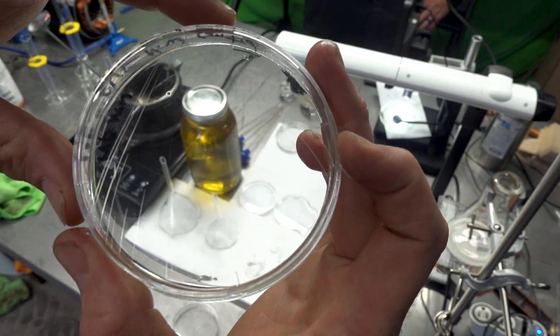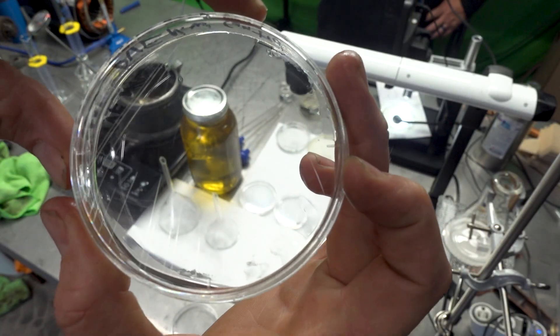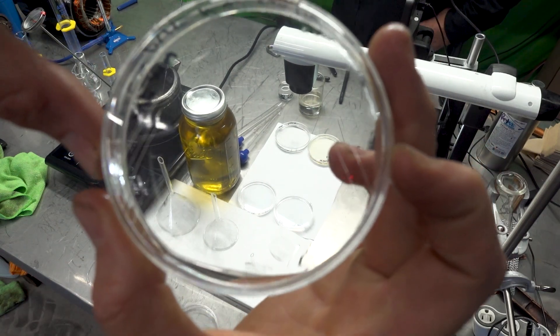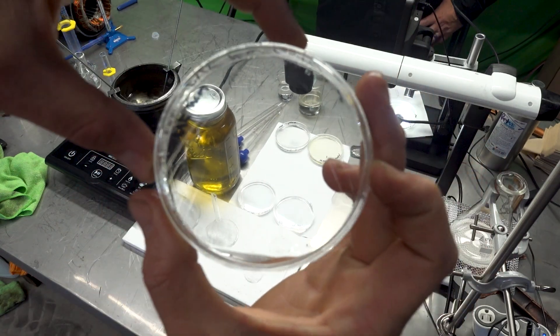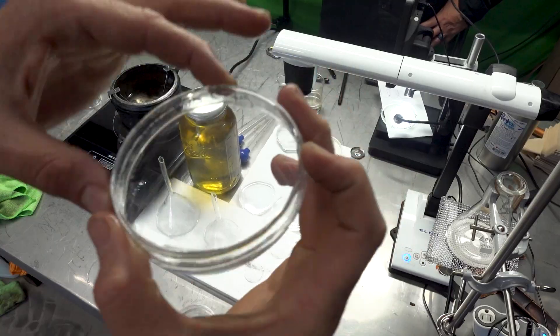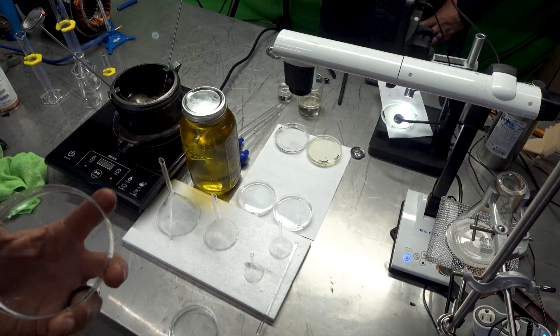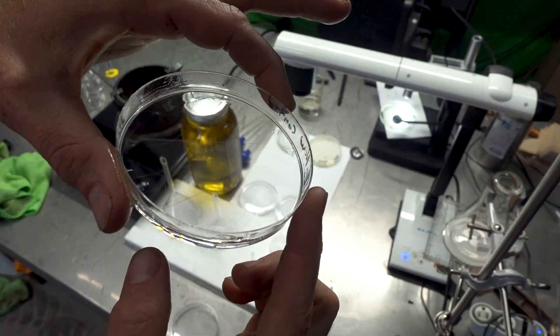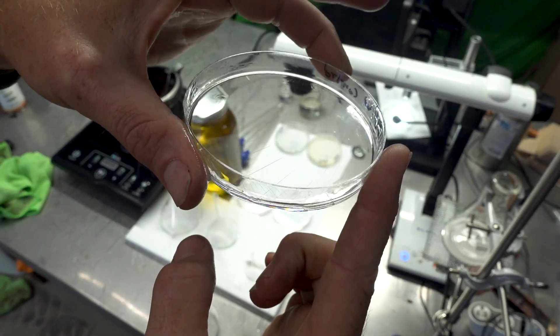As you're reflecting that side or moving it, the light's reflecting and I see even more cracks I didn't see before. One of them is going from one side all the way to the other, and they're going at different angles — so it's not just a manufacturing issue. It's actually how the oil is affecting the plastic, and some of them are deeper than others.